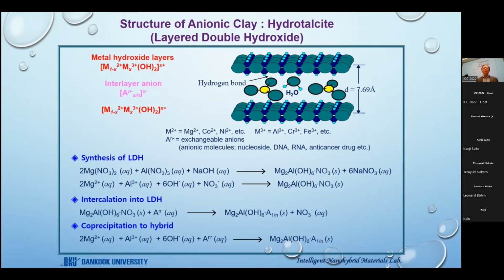However, depending upon the synthetic strategy, one can immobilize not only carbonate but also nitrate, chloride, halogenide, or acetate, whatever. Yeah. So in such a way, we can prepare the drug-clay hybrid by simple ion exchange reaction. For example, if you have negative molecules, one can immobilize the organic molecules into this two-dimensional lattice by simple ion exchange reaction, or you can prepare that kind of hybrid by simple co-precipitation reaction in the presence of salts, the anion species that you want.